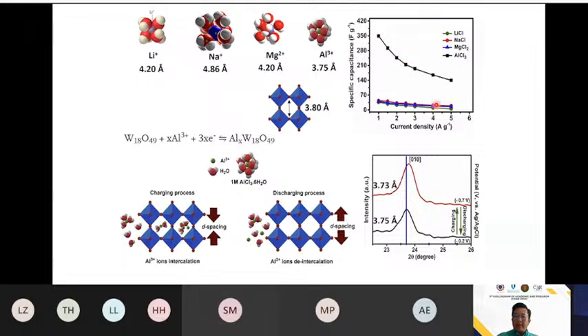The specific capacitance, the charge storage, is proven to be better than the rest of these, because the others are too big to get trapped inside. We run through the in situ XRD to really prove that the aluminum ion is really trapped during the charge and discharge process.